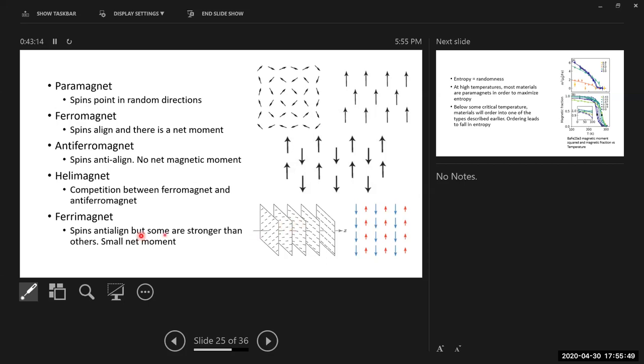They're very exotic. There's something called a ferrimagnet. So the first magnets that mankind ever discovered, some of the first measurements of magnetism were done by the ancient Greeks. They noted that if you took lodestones made out of magnetite, which is Fe3O4, iron oxide, they align with the Earth's field, but if you put it in a fire, it stopped aligning with the Earth's field. Magnetite is a ferrimagnet, where spins anti-align, but some of the spins are stronger than the others. So this leads to a weak but net moment in one direction.